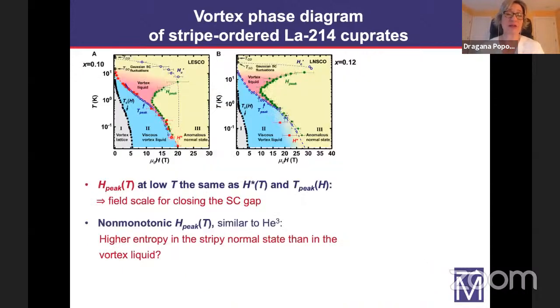So as I said, it's interesting that a peak in the magnetoresistance, at least at low temperatures, seems to correspond to the field scale for closing of the superconducting gap. And it is also peculiar that its position has this non-monotonic dependence on temperature. We do not understand the origin of that, but it is actually very similar to the solid-liquid melting line in the temperature-pressure phase diagram of helium-3 that was predicted by Pomeranchuk. So one might speculate this indicates that the entropy in this stripy normal state is higher than in the vortex liquid, which may be not so surprising. But in any case, at this point we do not know whether this boundary represents a true phase transition or this is just a crossover.